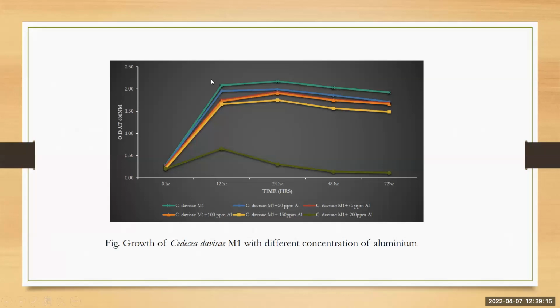So here's the graph. At the topmost, this is our isolate, Cedecea davisae M1 without metal. It grows maximum. After that, this is the blue line, in which we have put 50 ppm aluminium. As the concentration of aluminium increases, the growth rate decreases. That means the tolerance level also decreases. At 200 ppm concentration, the growth rate decreases drastically. So we can conclude that the maximum tolerance level of aluminium for the bacteria is 150 ppm.